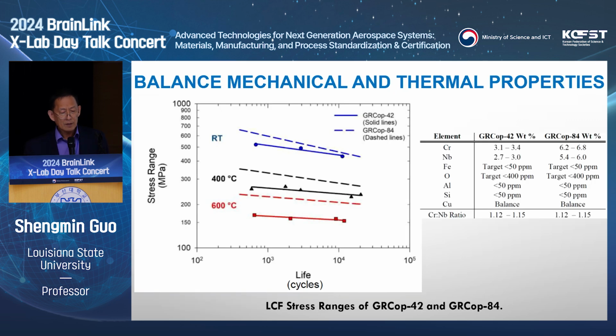heat them up. We tested the mechanical strength of GR-COP 42 and 84, two types of copper alloys. The only difference is the concentration of chromium and niobium. GR-COP 42 means I have around 4% of chromium with 2% of niobium. For 84, we have a slightly higher chromium concentration, close to 8% atomic level, and niobium is 4%. So with this unique composition, the GR-COP alloy can happily operate up to around 700 degrees C. At 700 degrees C, here I didn't show you.